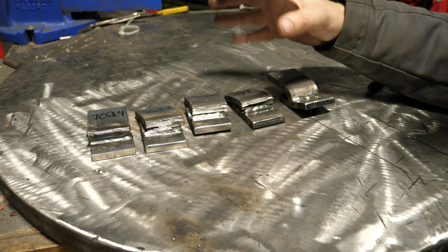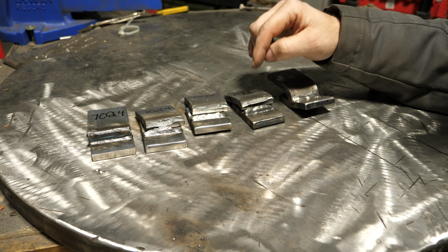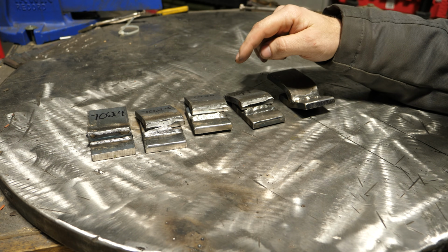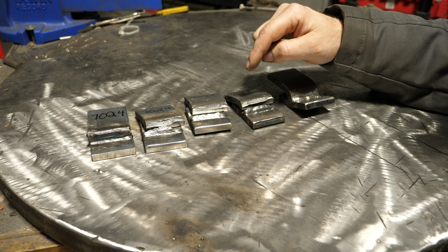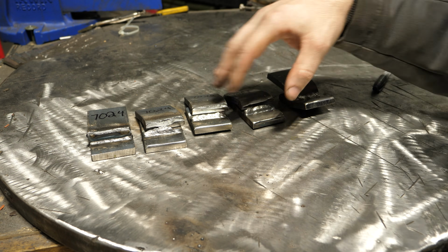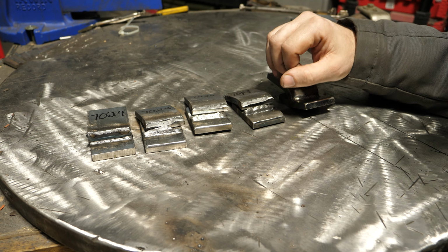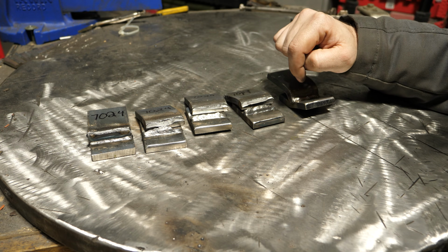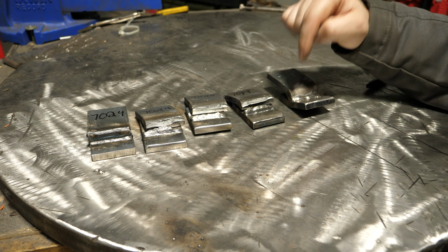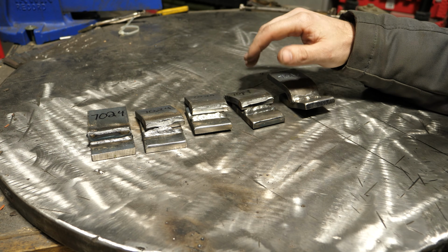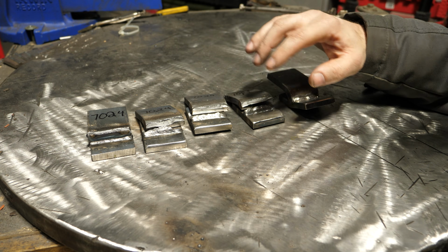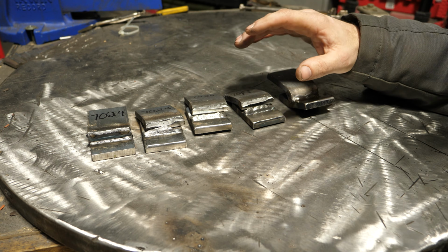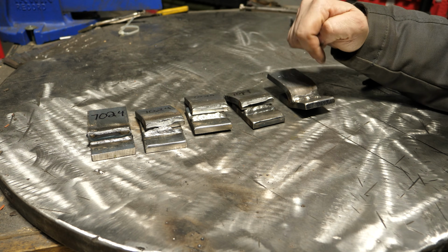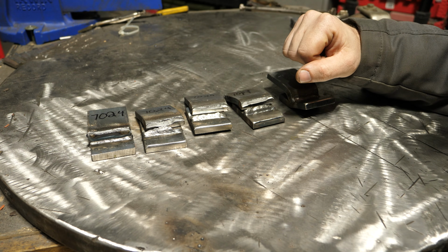And based on all the previous testing I've done on this, I'm starting to suspect that hydrogen embrittlement might be the root cause of why all the 70 series rods are failing and 70-18 is not, and ER70 MIG is not, and Dual Shield did not, even though the Dual Shield I haven't put on film yet. I did test a simple test, and it had no issue passing on a bend test away from the face.